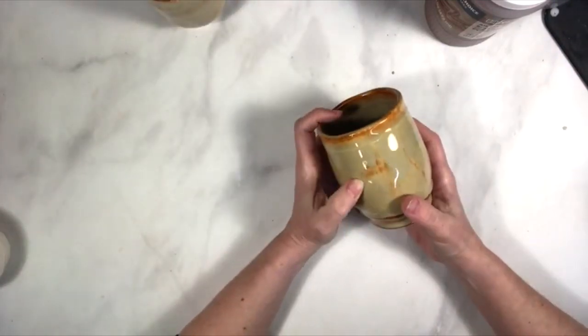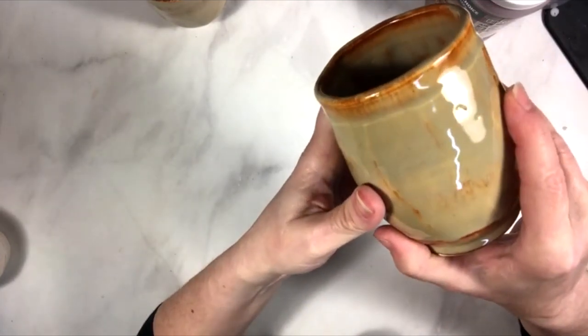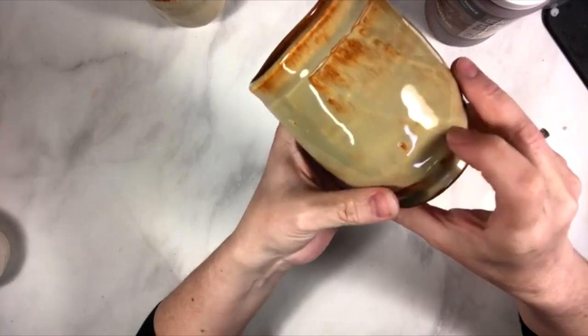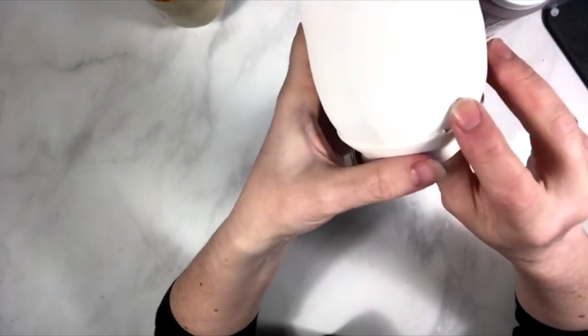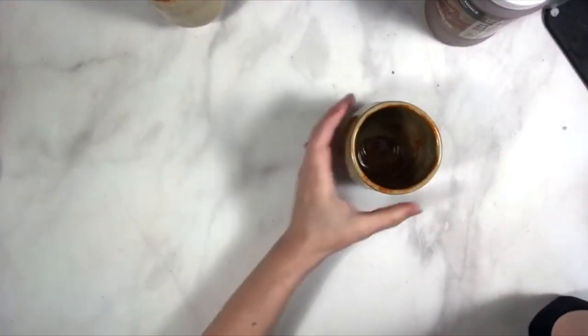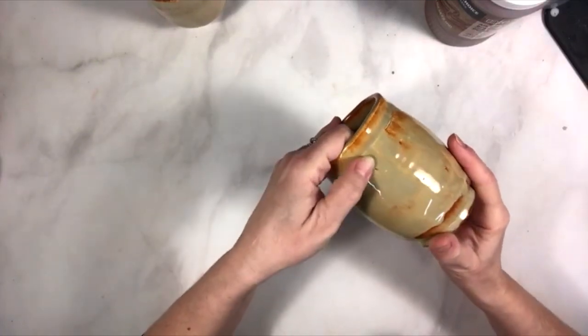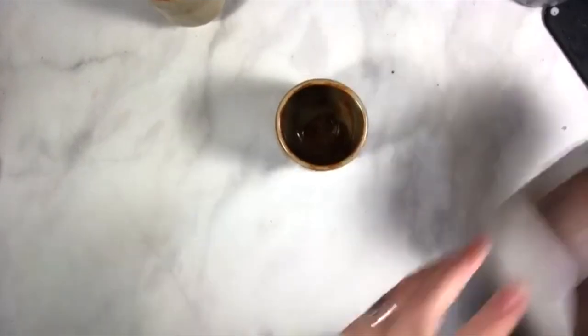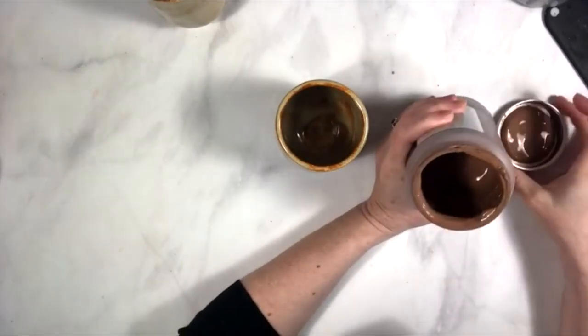Something I noticed when these came out of the kiln: you may see some tiny holes in the glaze surface. These are not pinholes in the sense of off-gassing. What's happened is the bisque cup has irregularities in the surface — it's not perfectly smooth — and if you have very tiny openings it can be really hard for brushing glaze to get into those because it has a high surface tension. The Chino line glazes are fairly thin but Albany Slip Brown tends to be a little on the thick side, which adds to this issue.